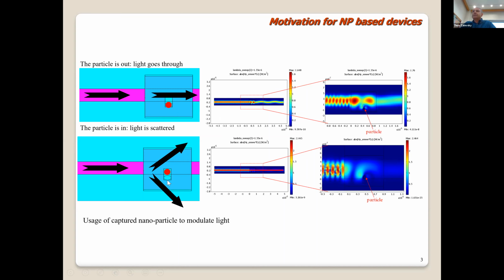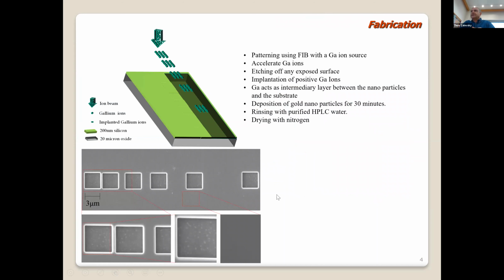On the other hand, if we apply an external electrical field, because the metallic nanoparticle is charged, it will be shifted. Even a shift of a few nanometers will cause scattering of the photons that are entering into this device, specifically if the plasmonic resonance of this metallic nanoparticle is matched to the wavelength of the guided photons. And then the efficiency of coupling light to the output of this device will be very low. So this is a modulator, a transistor that is based on the operability of this nanoparticle, but it is fully realized within silicon. Now, the question is how one can realize and fabricate such devices.